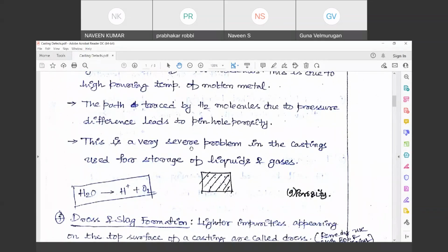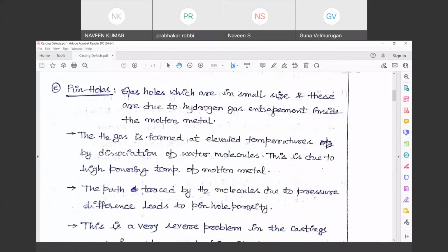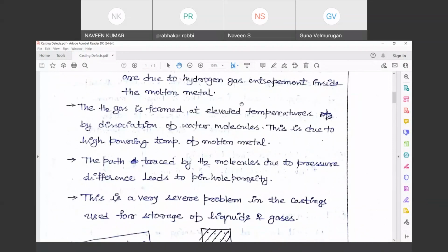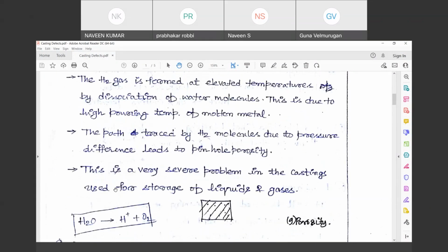Very severe. Why? These pinholes will travel in different paths, and small lines are formed inside. Very micro lines, dimension wise, and those are the places where cracks can develop very easily. As the crack is developing, what will happen? It will try to propagate. Those points might be the ignition point for a crack, and slowly over a period of time they will break under pressure. So that is the reason why this is a very serious problem in castings used for storage of liquids